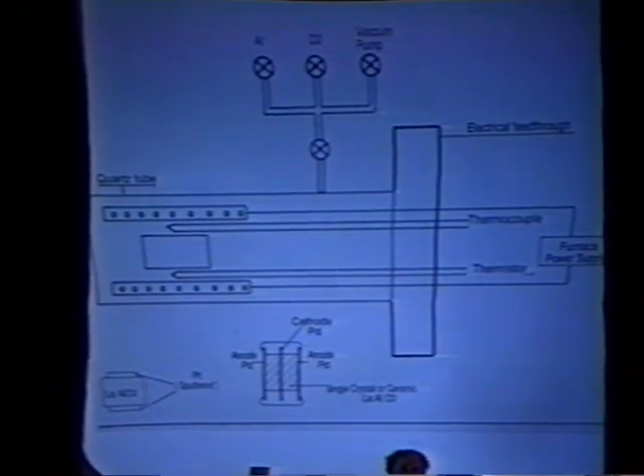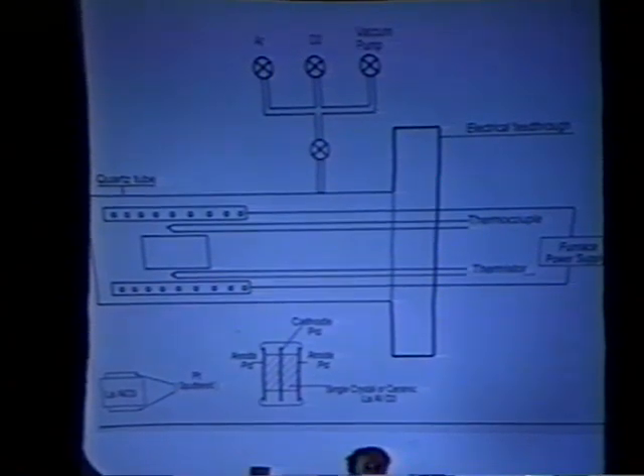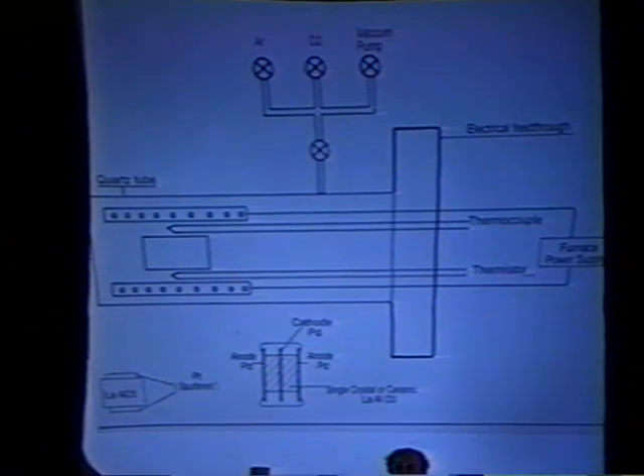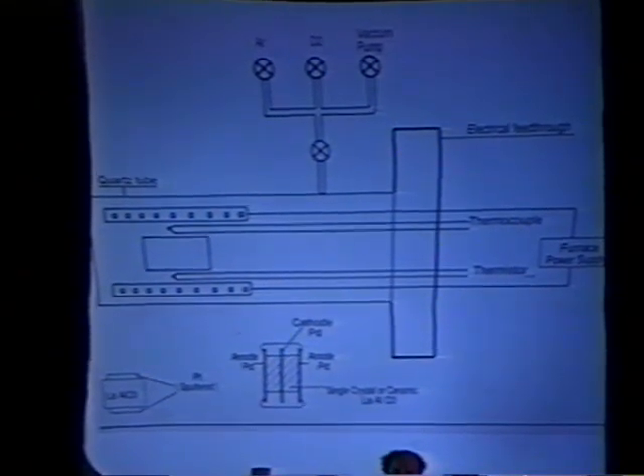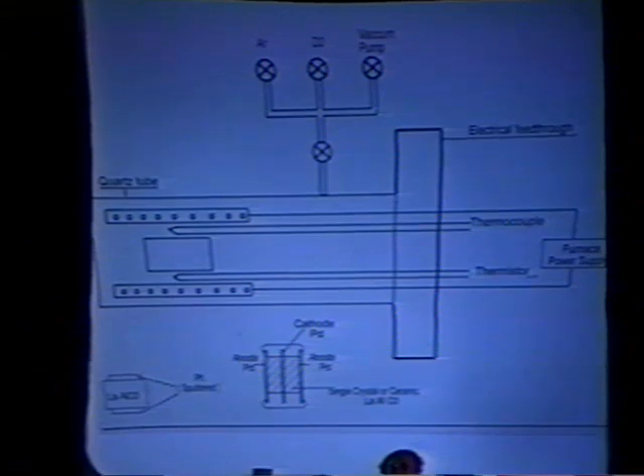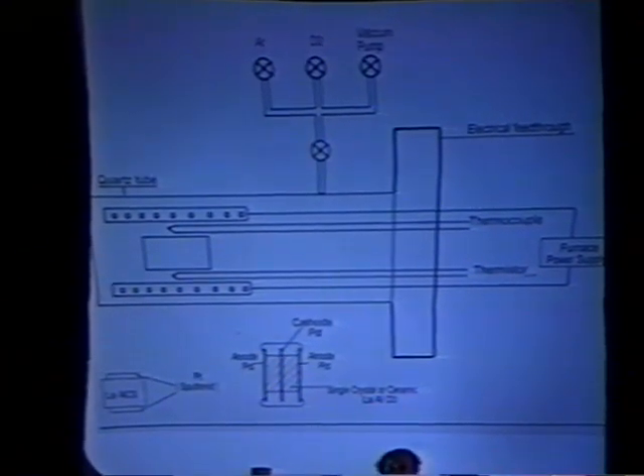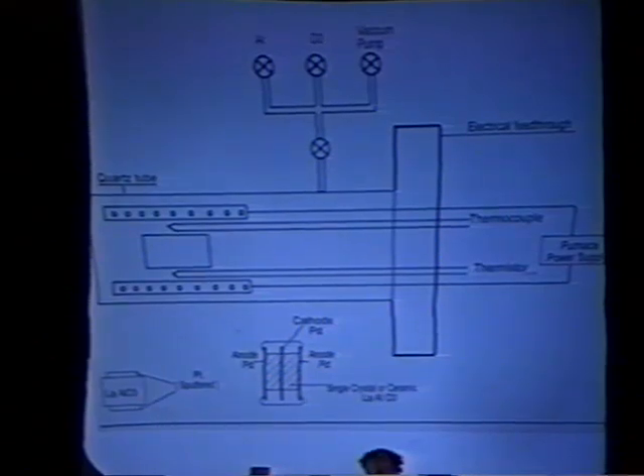So we are struggling and trying to make these ceramics or single crystals with lanthanum vacancies. Why lanthanum? Lanthanum has a valency of 3, aluminum has a valency of 3. If you take cerium, for instance, it goes from 3 to 4, whereas lanthanum will always be 3. So you can make a material with lanthanum vacancies, and you can fill it eventually with 3 hydrogen or 3 proton, 3 deuterium. And if you apply voltage to that system, you might go even higher concentration in every one of these vacancies.